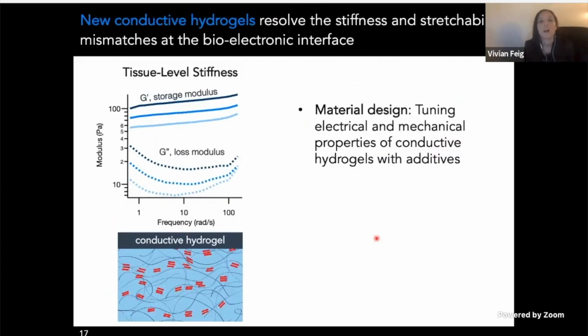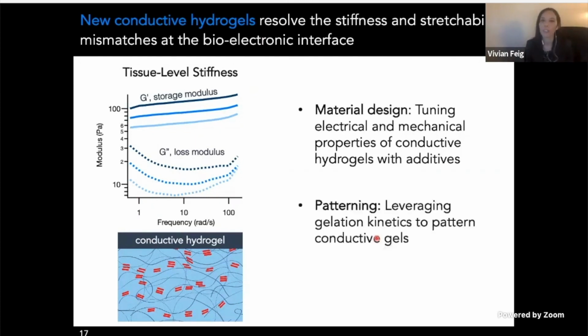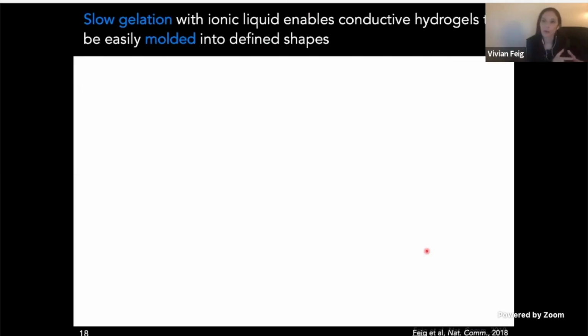So now that we have an idea of how to design these electrically conductive soft materials, the next thing I want to talk about is how we can leverage different gelation kinetics to actually pattern them in different ways. The first way came about when we were working with those conductivity enhancing ionic liquids, and we noticed that compared to other additives like metal salts or acids, the gelation of PEDOT:PSS in the presence of these ionic liquids happened over relatively long timescales. To test this, we can mix the solution with ionic liquid and then use a rheometer to monitor the gelation time.